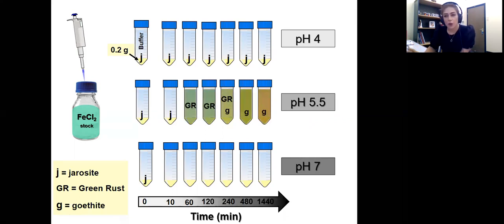After about 1 hour, I observed the formation of a new phase, and it was obvious from the color change in my samples too. Then we analyzed our samples using XRD, and after that by X-ray absorption spectroscopy. With synchrotron X-ray absorption spectroscopy analysis, we made sure that this phase that occurred 1 hour following the addition of iron 2 was green rust.